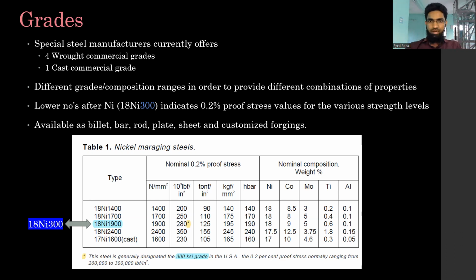Firstly, it heavily lowers the martensite start temperature, as we discussed. It retains the austenite as well and avoids complete transformation to martensite. So lath martensite is replaced by twin martensite. This is another issue. Martensite that is formed should be lath martensite, which is desired. Twin martensite is not desired. And this twin martensite will be formed when the nickel percent is off. That is another thing. It retains austenite in the sense that any change to the 18% retains the austenite. So you have to have this 18% for the austenite not to be retained, and to avoid incomplete transformation to martensite.